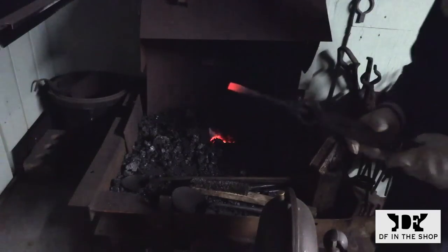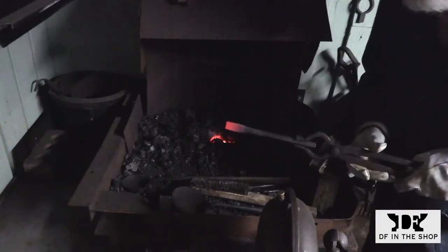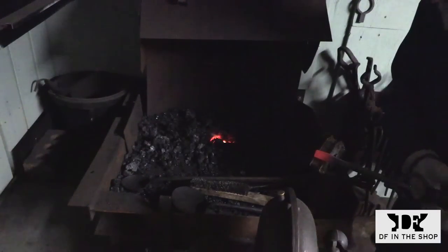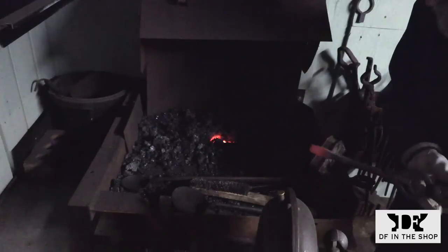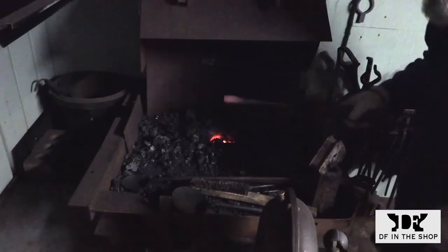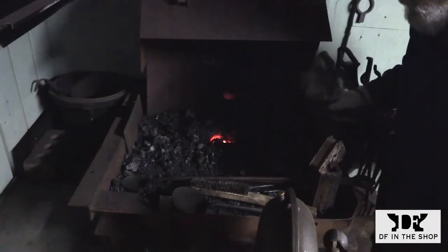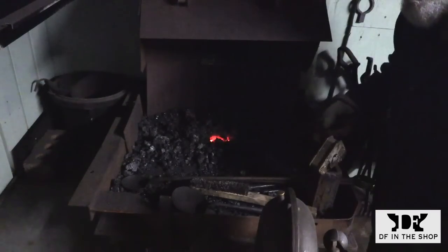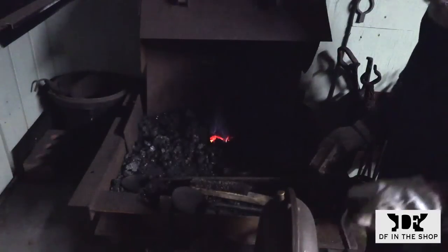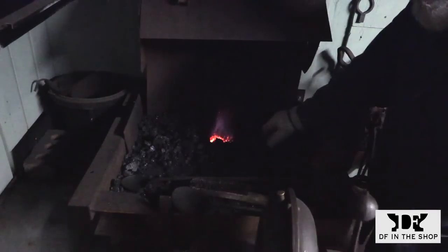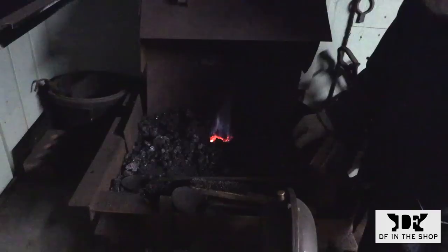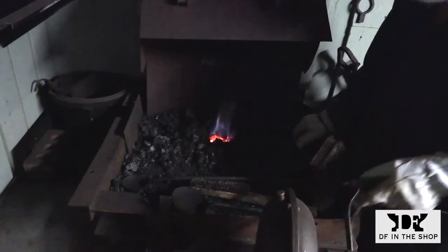So here I've given it just a little bit more heat. It's brighter, but it's not dramatic. And at this point, it is no longer magnetic. So this is the critical temperature for this steel. If I heat it beyond this point, it'll still be non-magnetic, but the grain structure within the steel is going to keep getting larger and larger the more I heat it up.